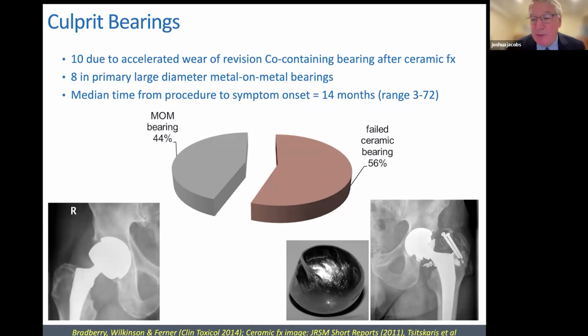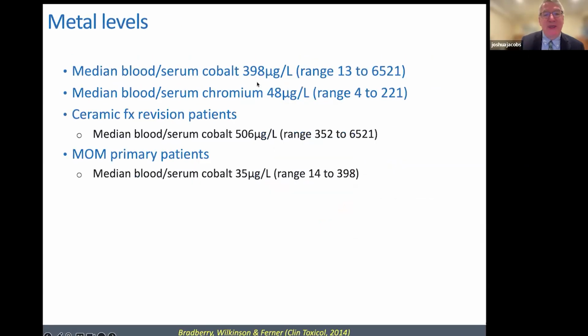And if you replace the head, for example, with a metal head, it can lead to disasters like this, where the ceramic debris erodes. This used to be a sphere, and you can see all the metal that's been eroded. What can happen in this situation is that the mean blood cobalt levels can be dramatically elevated. Remember, the normal value is 0.3. So this is 4 orders of magnitude elevations in serum blood levels.